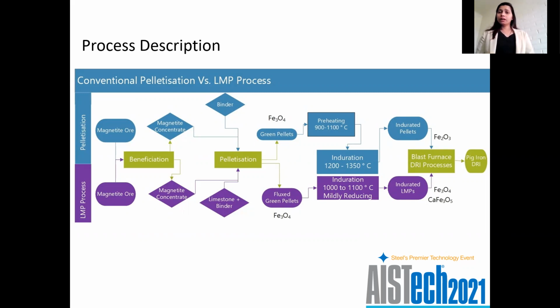Now, what we are doing here is we deliberately oxidize magnetite to hematite and then charge it to the blast furnace and take out that added oxygen with additional fuel or additional carbon. The reason we do that is because magnetite has lower reducibility compared to hematite, and we need to oxidize it to hematite to charge it to the blast furnace or DRI processes. So with the LMP process, we avoid that magnetite oxidation stage.